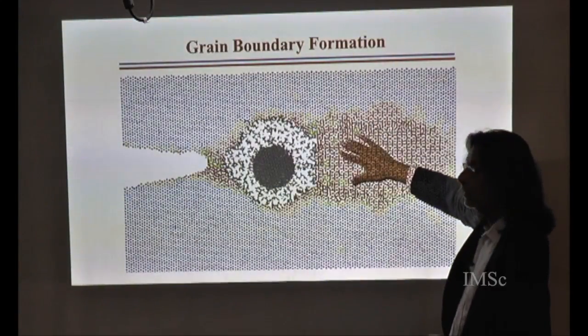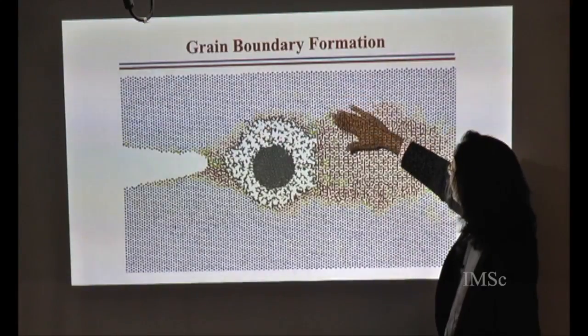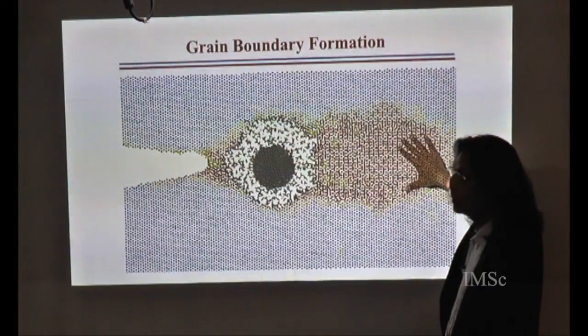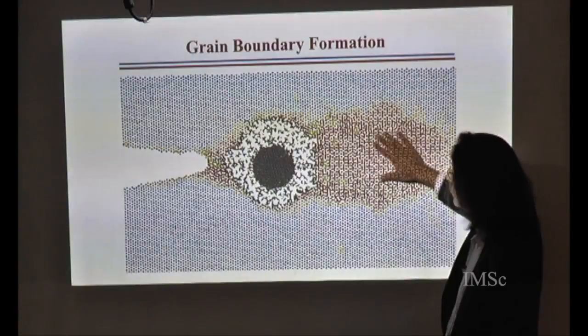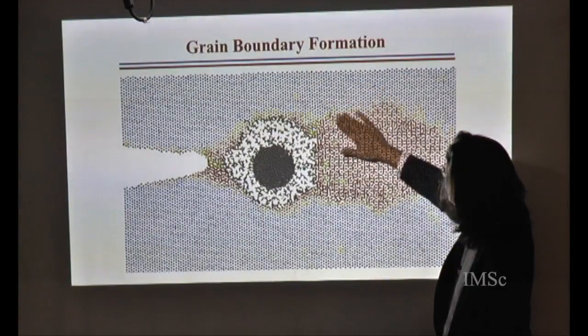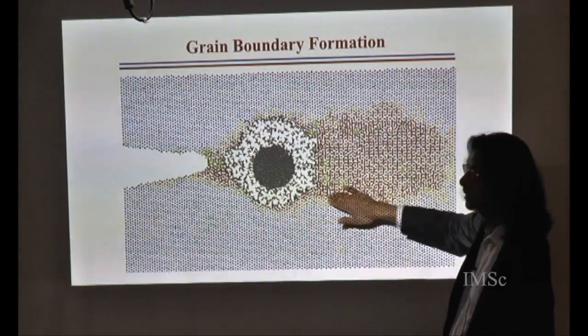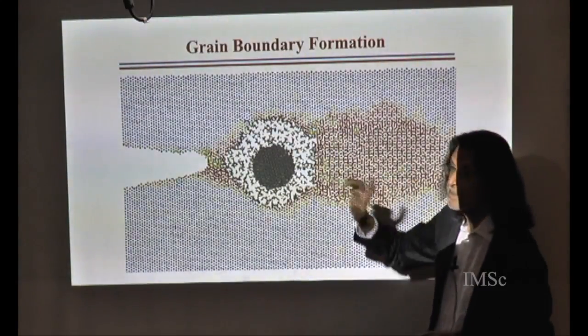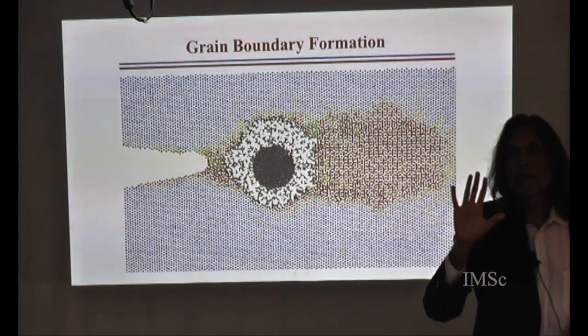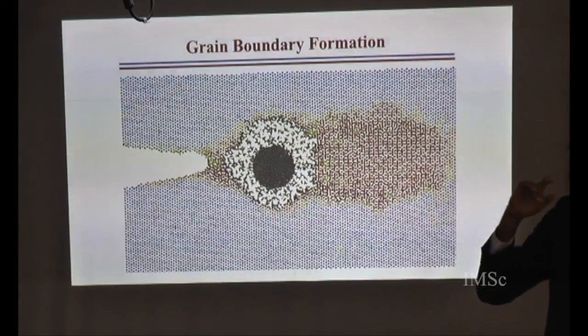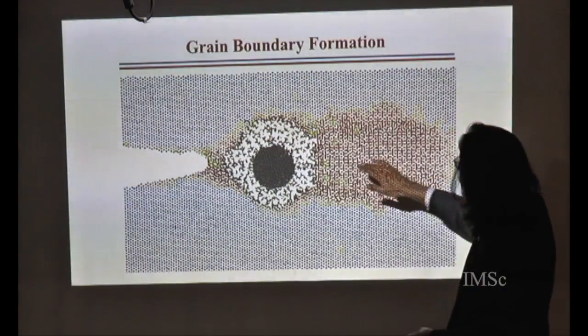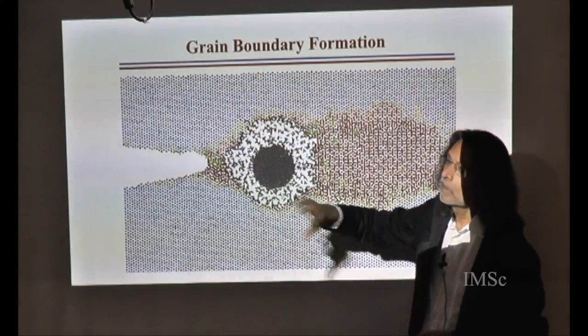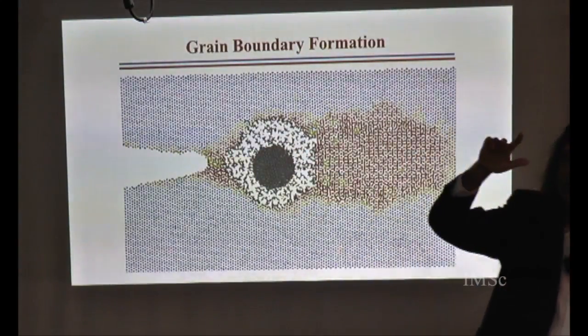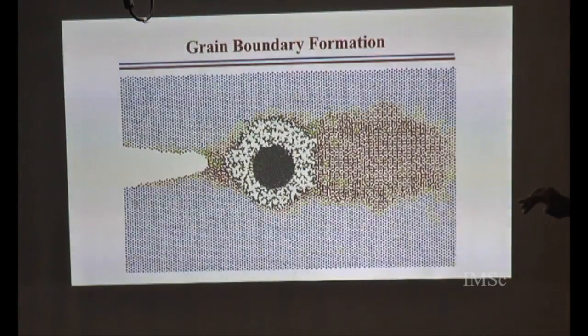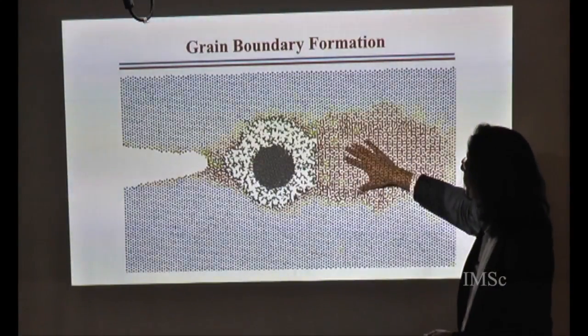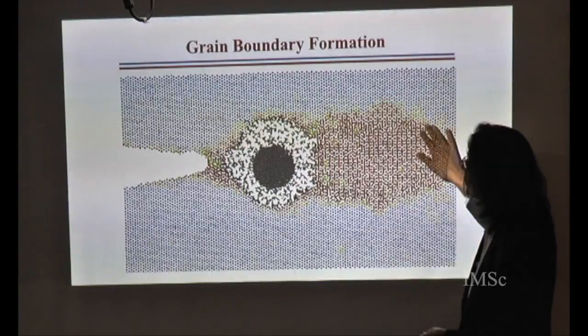So over here, you can see there is one grain over here. The crack has not gone through here. So there's one grain over here, one grain over here, and this is sort of the grain boundary. So from this system, with nanoparticles repairing the crack through the flow of silica, the additional thing we see is that these silicon carbide nanoparticles rotate. And when they rotate, we see the formation of these grains. So there are grain boundaries in this system.